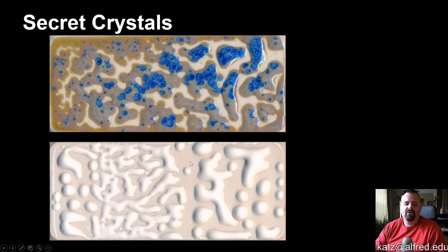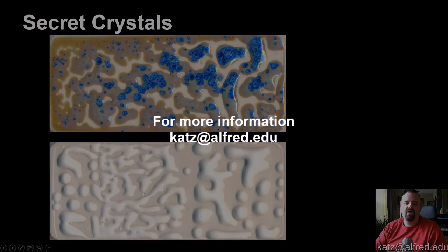Now, the one thing I will say about crawling and glaze application is, it's sort of hard to see, but if I draw a line here, the crawls on this side are super fat, and on this side, they're much skinnier. And what this is, is 2 dips on the fat side and 1 dip on the skinny side. So the thicker the application, the more the glaze crawled into big crawls versus